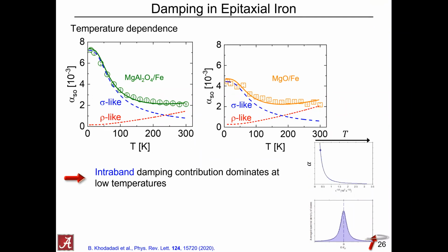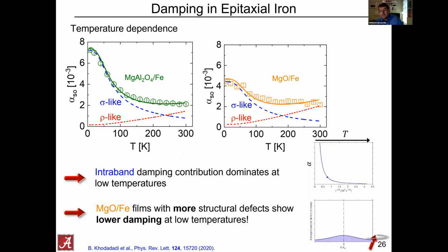Yes. It seemed quite a clear separation in Parkin's work, and they said there must be two different mechanisms for bulk and the surface, which was interesting. Because, as you probably know, I don't believe in intra-band transitions, so I'm always looking for a different explanation of these conductivity-like results. In our paper, if that interests you, there is data from other film thicknesses in the supplement, and this behavior that you see here, you see it in thinner and thicker films, so it's not an artifact of this particular thickness. Okay, thank you. More questions?